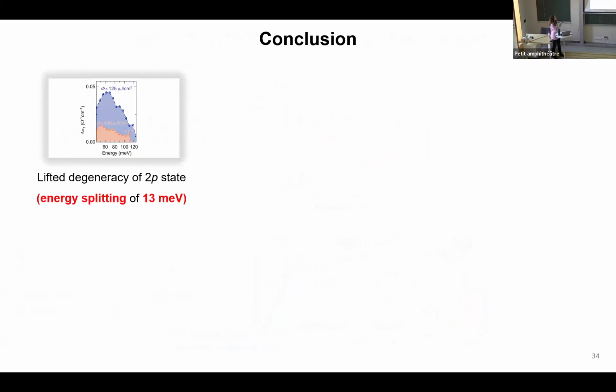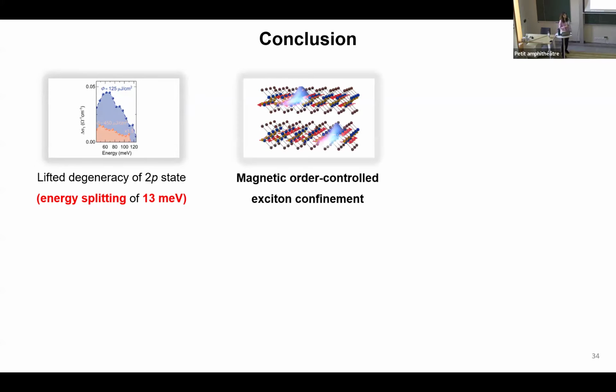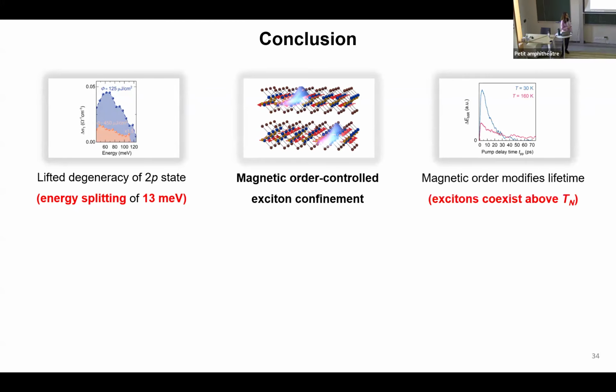I have come to the end of my talk, and the take-home messages. I hope that I convinced you that actually in the case of the bulk chromium sulfide bromide, the high anisotropy of the dielectric function lifts the degeneracy of the 2p states by a very large value, at least about 13 milli-electron volt. And we also saw that the magnetic order controls the internal structure of these excitons. And not only that, it directly influenced the ultrafast recombination dynamics of the excitons, as we could follow both below and above the Néel temperature.